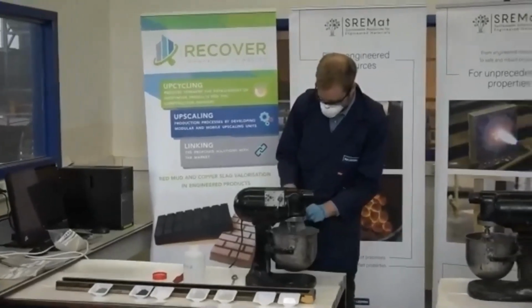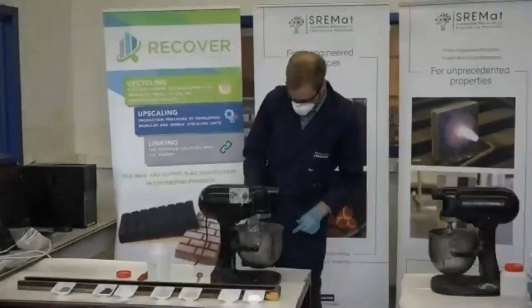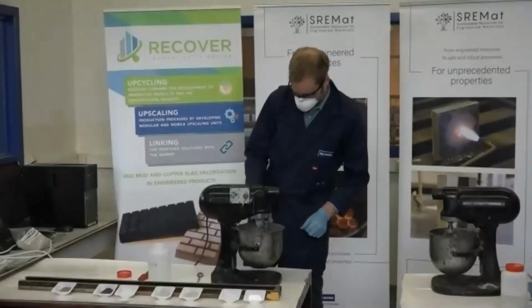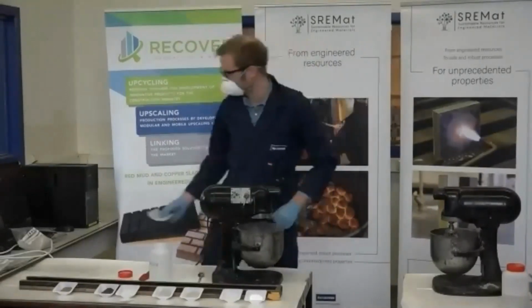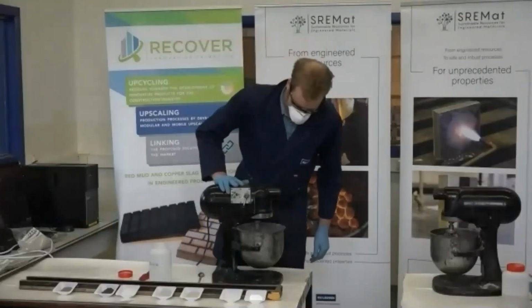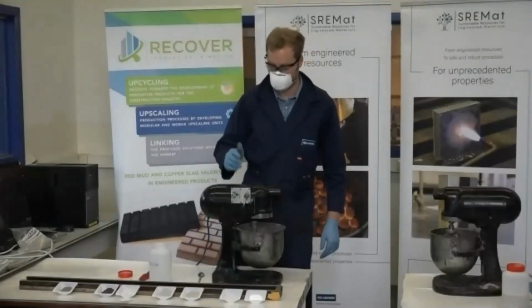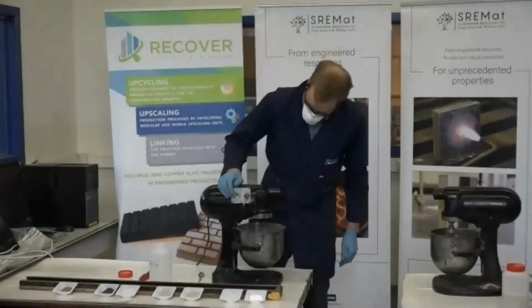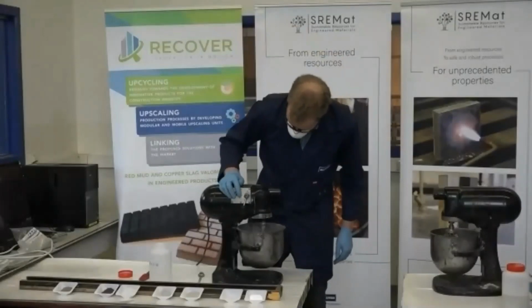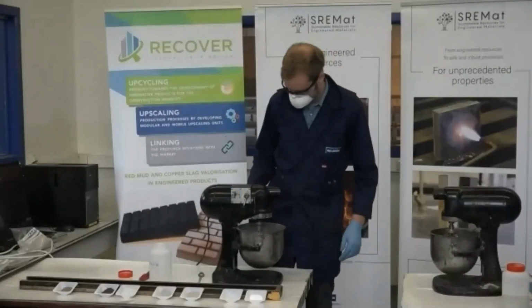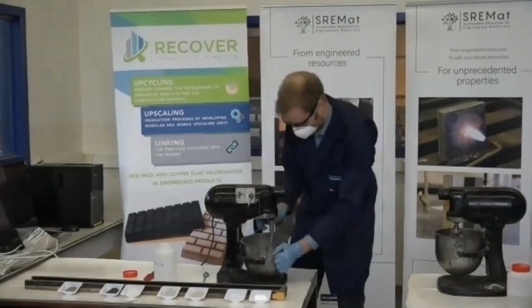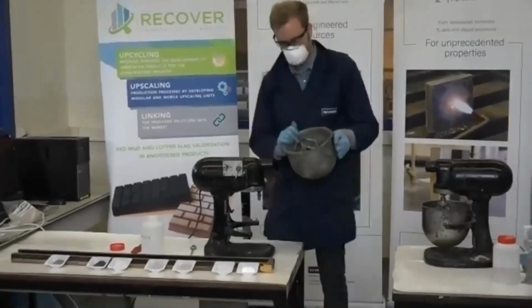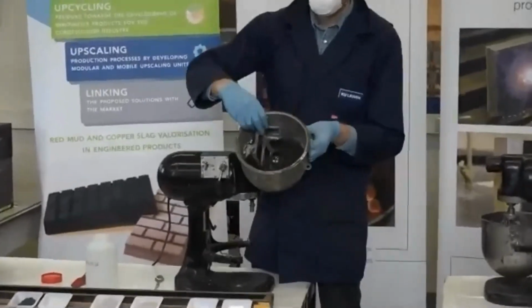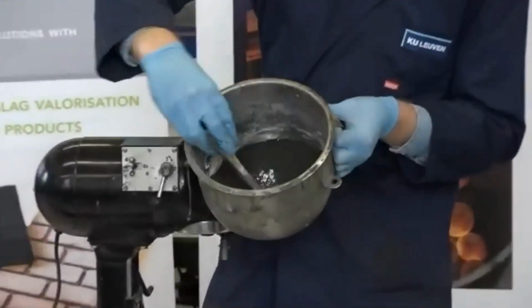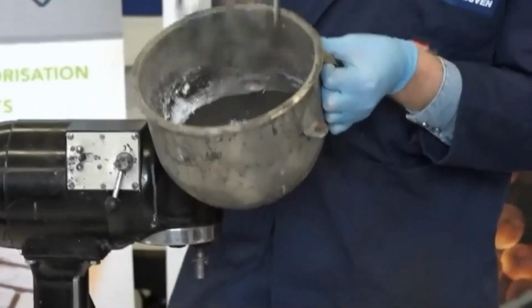So you see it's a rather small amount that he adds, in this case around 1%. Maybe you can hear it already, the mix is changing at that moment. It takes some time to homogenize it well in the mix. But I think you can clearly see now the difference of the paste. It is almost like liquid.